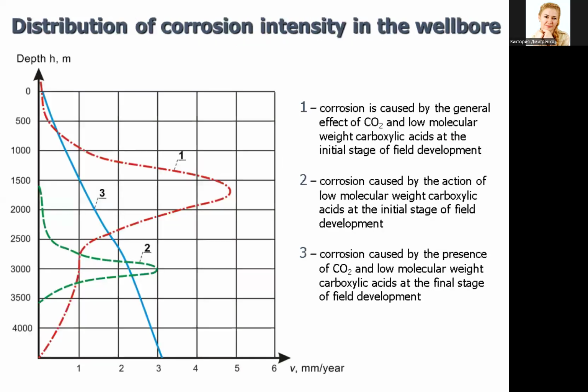It has been established that the interaction of organic acids with metal occurs in the Dnipro-Donetsk basin fields in the temperature range of 90–110 degrees Celsius and at a depth of 3,000–3,500 meters. The interval of action of organic acids on metal tubing depends on the constancy of the regime and operation time of the valve. In the constant mode, the effect of organic acids is limited to 100–150 meters. The effect of corrosion under the influence of organic acids is especially pronounced in wells where the carbon dioxide content is insignificant, with carbon dioxide pressure less than 0.02 megapascal.